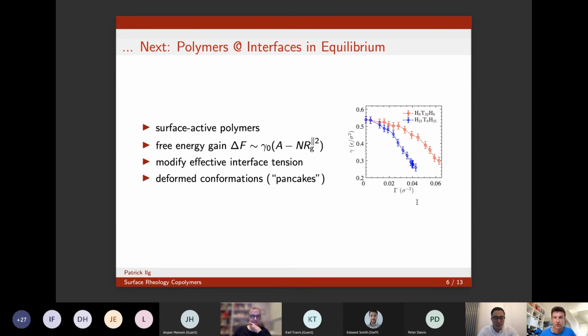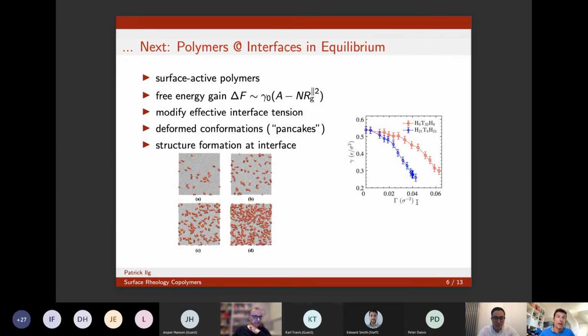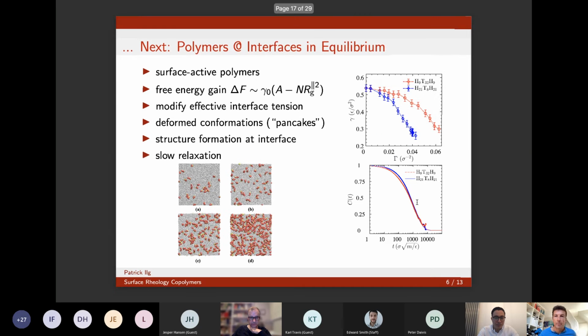Okay, so what we see is that we have these deformed conformations, and also a 2D structure formation of these polymers. There are some snapshots on the left, and we did some grand canonical Monte Carlo simulation and also some density functional theory to work out what would be the effective gas-liquid coexistence of these systems. That's not of relevance for this talk, but what is relevant is a slow relaxation that we see in equilibrium dynamics: this is the end-to-end vector correlation function of these two pluronic molecules at such an interface, and they are slowly relaxing indeed.